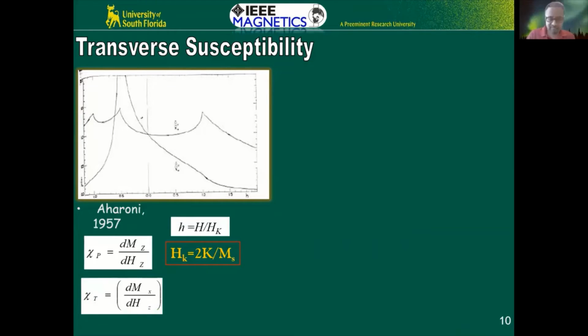In fact, here's a plot, reduced field with respect to the anisotropy field. If you go from positive saturation to negative, for the parallel susceptibility, as you would expect, you see a singularity. This is like taking the first derivative of your hysteresis loop. So when the spins are switching, when you change the polarity, where the maximum slope changes, you get a peak. So it's a singular point detection.